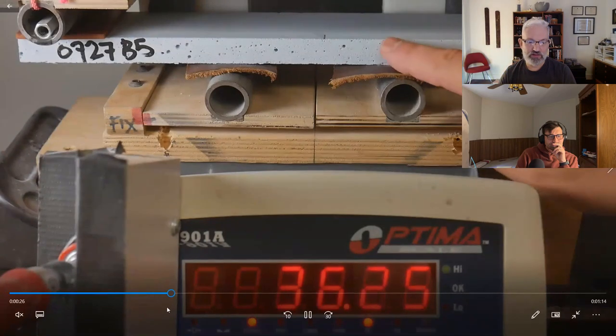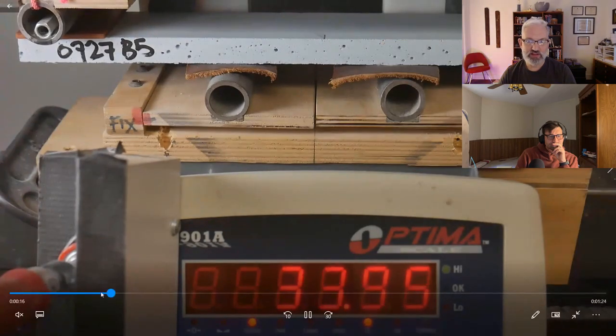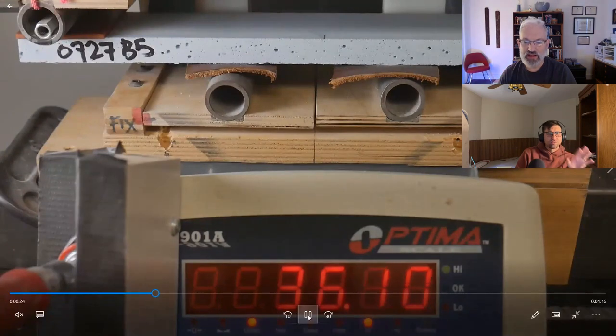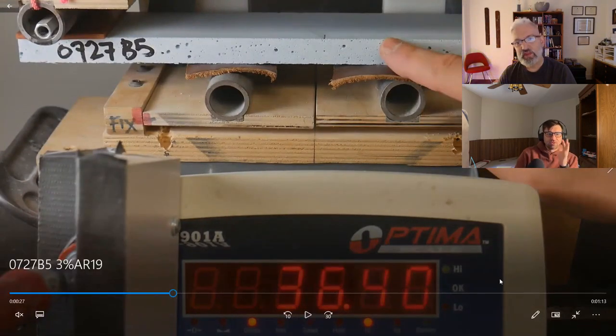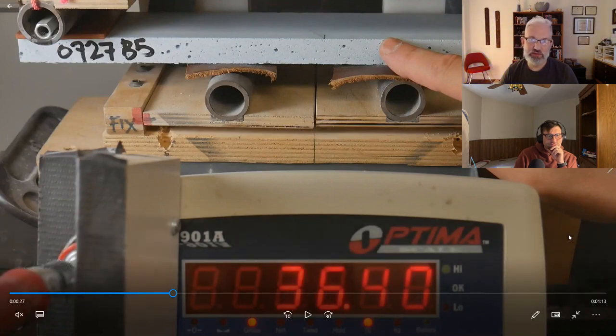What happened there is, yeah, it's got a little more voids in it, but the casting surface is pretty flawless. And remember, this is at 3% fiber, so you can't compare that with something that's 1.75% fibers. You guys probably can't see it, but I can see a little hairline crack that formed. That's called the limit of rupture, and that's the strength that we care about.